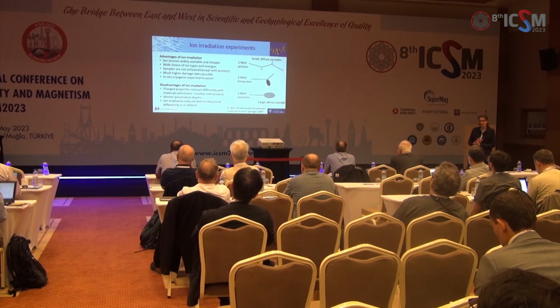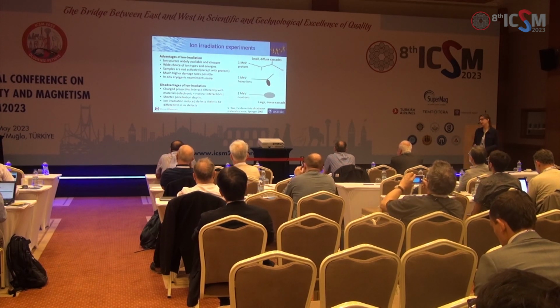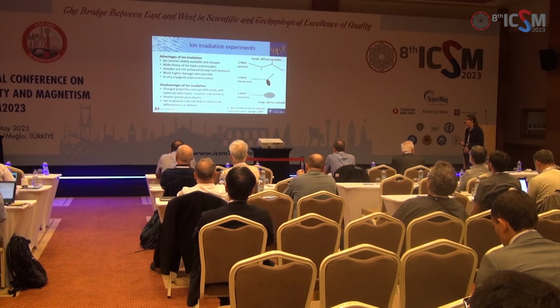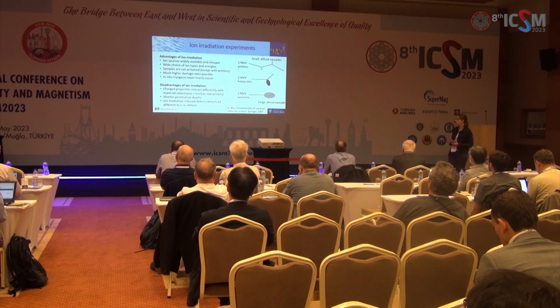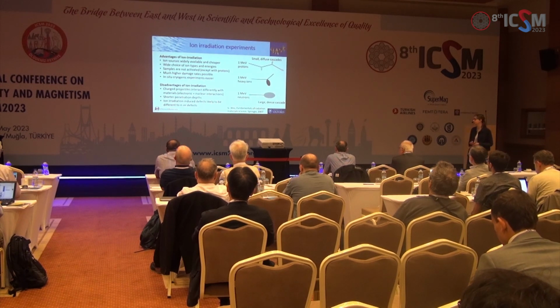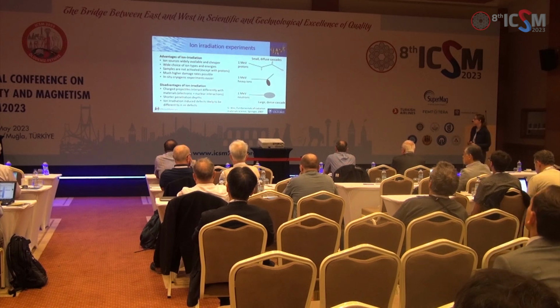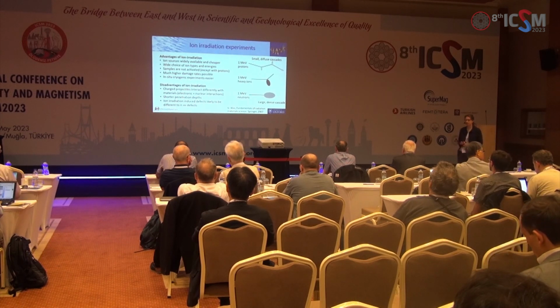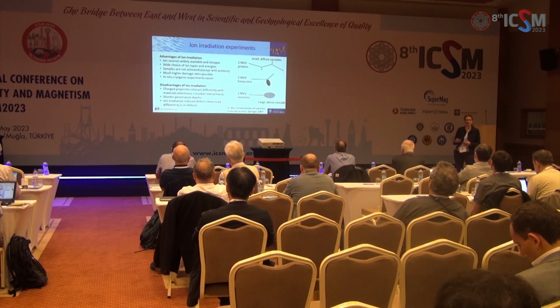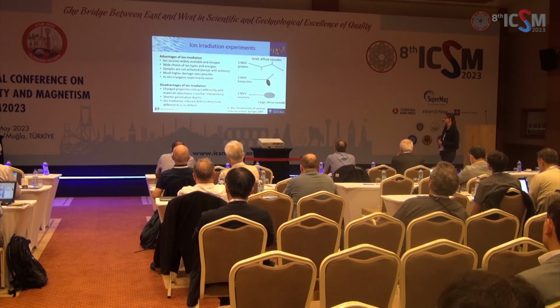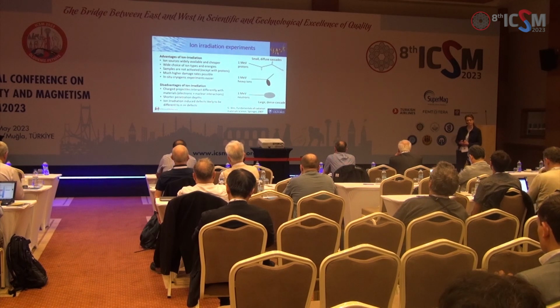So what could we do instead to get more results more quickly and more easily? We could use ion irradiation instead. Ion sources are much more widely available. You've got a wide choice of what ion you use and what energies you use. The samples don't get activated unless you're using protons. And you can get much higher damage rates much more quickly because they're charged species, so they interact slightly differently with the material. It also makes things like in situ experiments much easier.